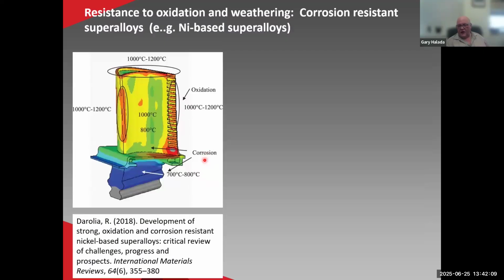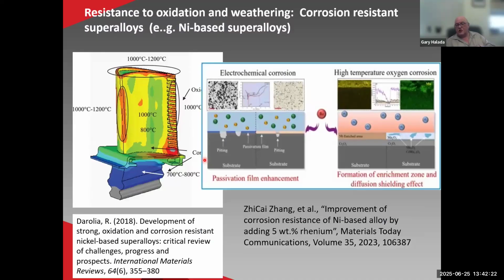Probably one of the more exciting areas that have been developed recently are nickel-based superalloys like Hastelloy, and new ones being developed. These are good in very high temperature environments, because high temperature corrosion or oxidation is obviously something that forms under extreme conditions. And so these high nickel-based alloys, these nickel-based superalloys, can prevent both electrochemical corrosion by helping to form a very durable passive layer or oxide layer on the surface, and also can help prevent high temperature oxygen corrosion by forming a layer on the surface that prevents the diffusion of oxygen into the material while it's heating, limiting the thickness of the oxide layer that forms. That's why you can use it in turbine blades and areas like that.